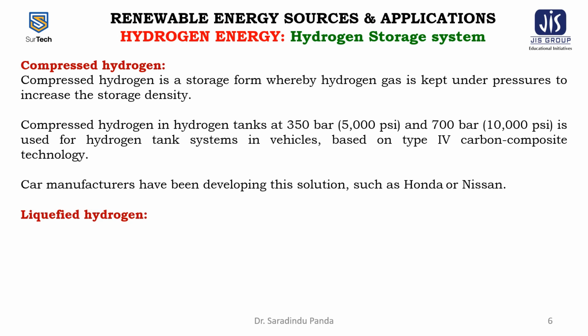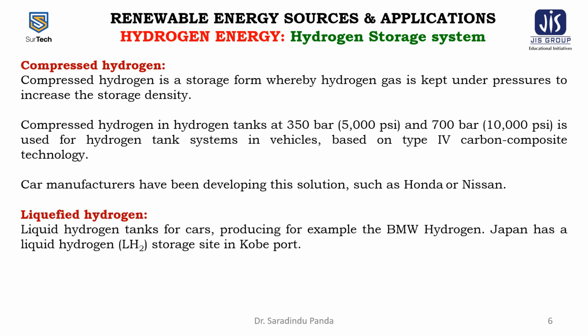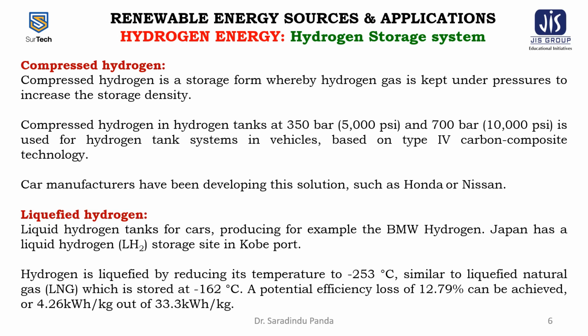Another storage form is the liquefied hydrogen. The liquefied hydrogen tanks for cars are produced, for example, by BMW. Japan has a liquid hydrogen storage site in Kobe Port. Hydrogen is liquefied by reducing its temperature to minus 253 degrees centigrade, similar to liquefied natural gas, that is called LNG, which is stored at minus 162 degrees centigrade. A potential efficiency loss of 12.79% can be expected, or 4.26 kilowatt hour per kg out of 33.3 kilowatt hour per kg.